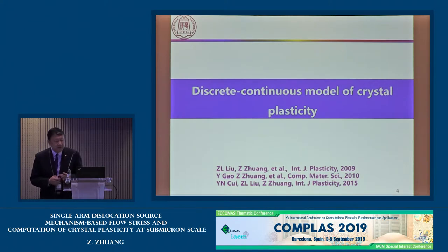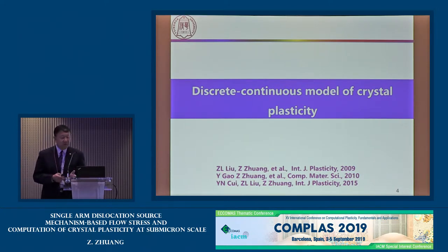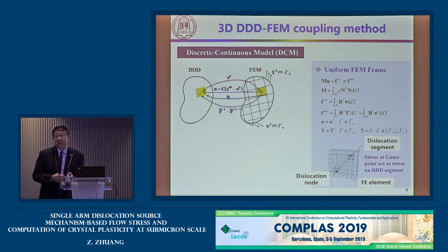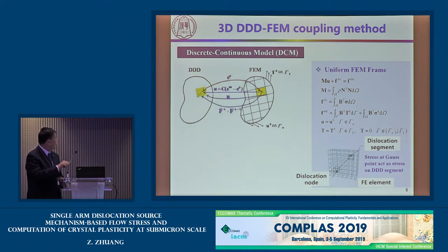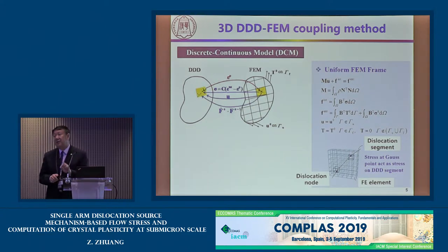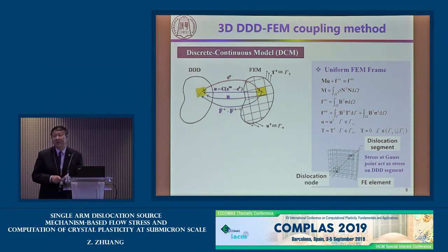For this work, we started in 2004 working on dislocation dynamics, and also on a discrete-continuum model for crystal plasticity. We treat the problem as a finite deformation. We use the DD dislocation dynamics model together with the finite element method — dislocation dynamics drives plastic strain increments passed to the finite element Gauss points, which in turn pass deformation and stress back to drive the DD motion.